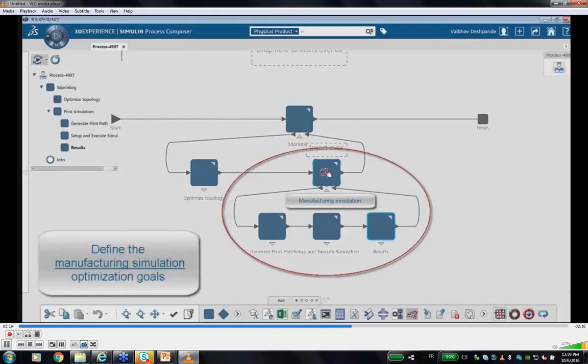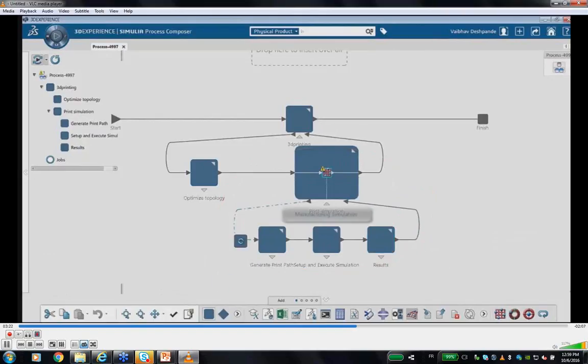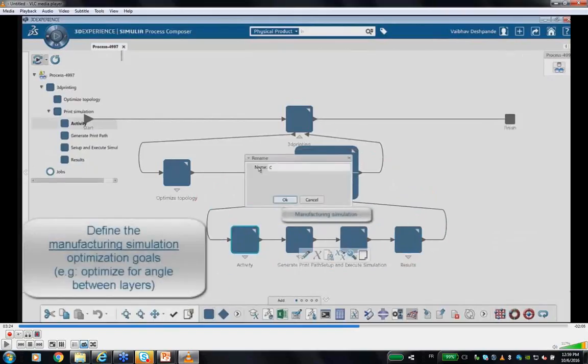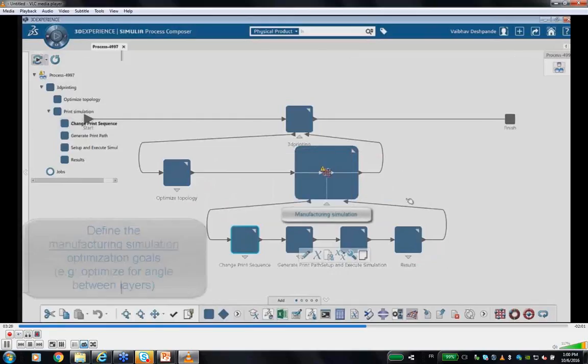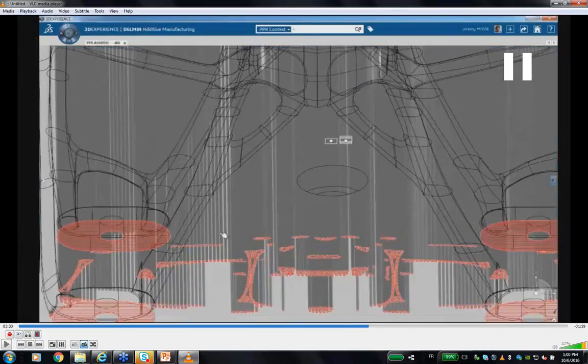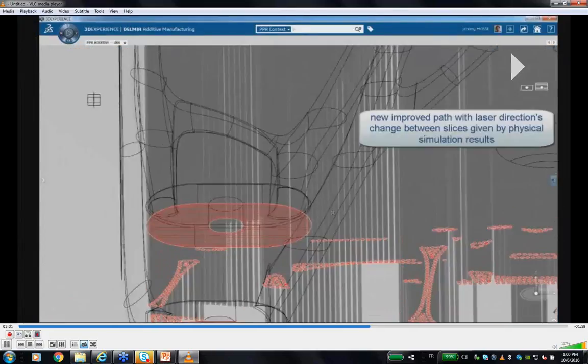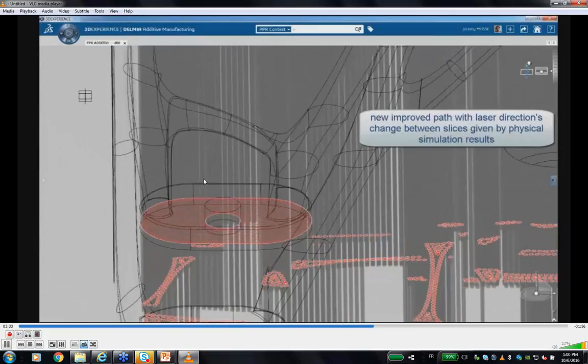And here the idea was, as a demo, just to show you how we can, for example, play on one of the parameters to do so. The parameter we selected for this demo is to change the orientation of the lasing path between consecutive layers. So we'll put an angle. For the first layer, it will be a given angle. For the second layer, we'll rotate by a given angle. Let's change by 45 degrees. So for the first layer, we have this, and for the second one, we have a 45 degrees rotation of the path, and so on and so on.